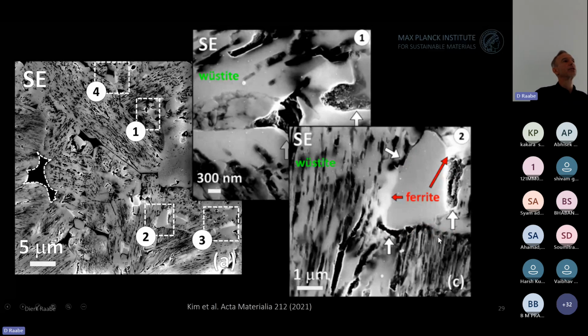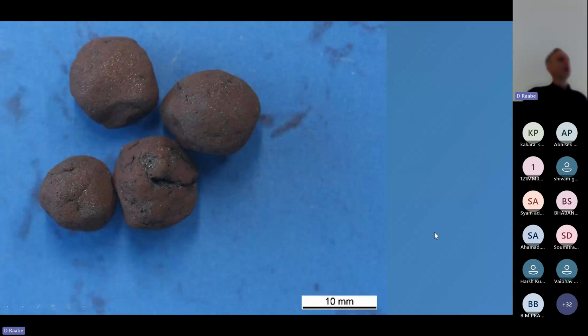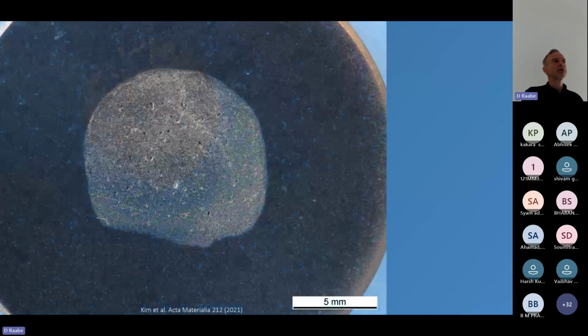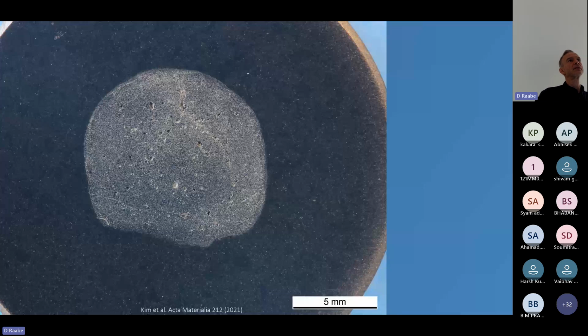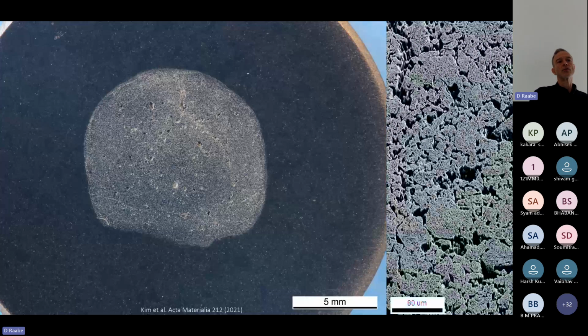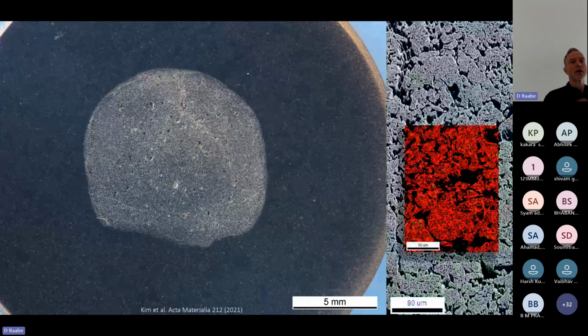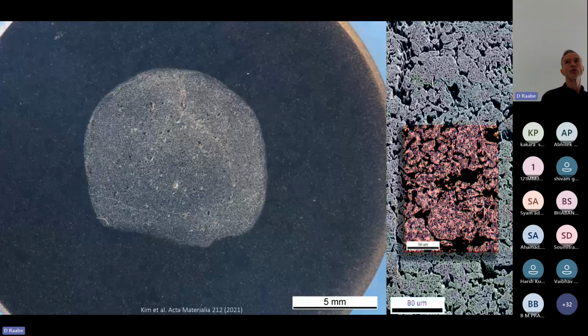That is quite important to understand. And when you go now to the pellet scale, to the polycrystalline sintered pellet scale, here you can see that they have an average diameter of 1.1 centimeter. And take out one of these now in a polycrystalline state in the sintered condition, then you can do the same type of microstructure analysis that I have shown to you before.